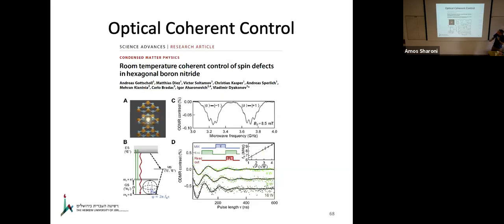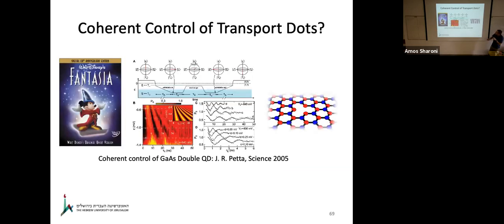Where do we want to reach? What people have managed, this is Igor Aharonovich and Vladimir Diakonov, showed that you can look at these defects in hexagonal boron nitride and then tune them as quantum objects, as cold atoms or as NV centers, tune the quantum states using ODMR techniques or NMR techniques with microwave frequency, etc. Now, people did that with quantum dots using gallium arsenide. Now, the dream here, the fantasy, is can you do quantum control of a defect in the same way that people have done that?